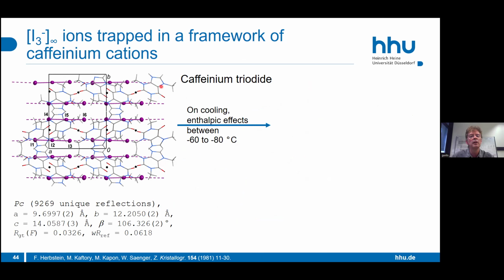wireframe diagram. Within this wireframe diagram, you also see these black dots. They represent inversion centers. That means this hydrogen bonded framework of caffeinium cations has inversion centers. But if you look at the I3- anions and their arrangement to each other, you see it doesn't fit with the inversion center. So it's not a surprise that we have a non-centrosymmetric space group.